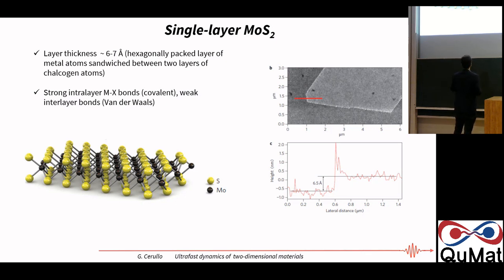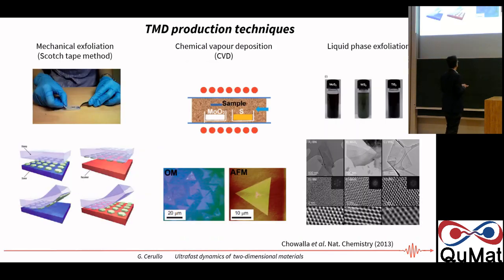And you can exfoliate it, but nowadays there are many techniques to make these materials. Of course, exfoliation typically gives you rather small samples. They can be of very high optical quality, but this is the Scotch tape method. You can grow them by chemical vapor deposition. They typically tend to form these triangular islands, and there you can cover really large areas with the material, but these materials have more defects. You can have different kinds of defects that Zeila is studying quite in detail.